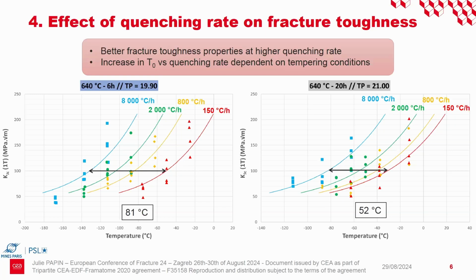We have 81 degrees versus 52 degrees, and this is 30 degrees between the 2. So this is a high impact of the quenching rate on the reference temperature.